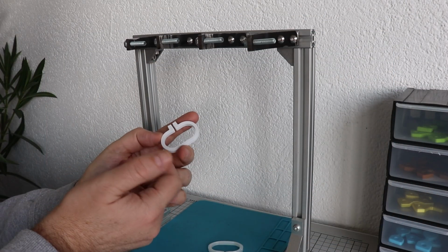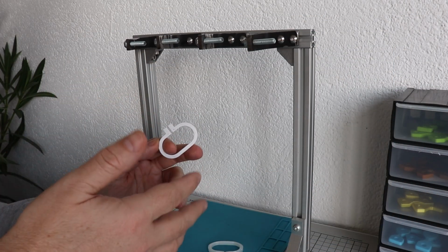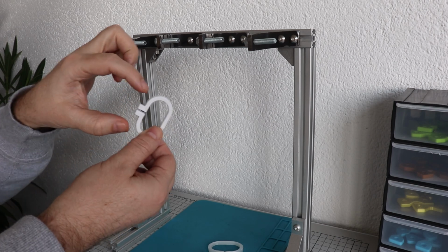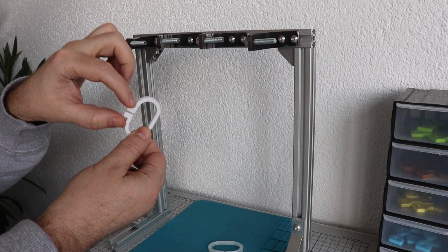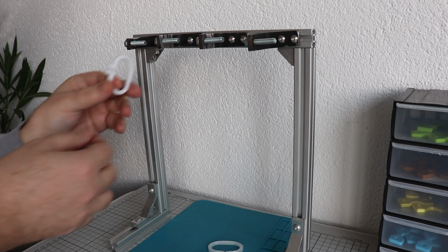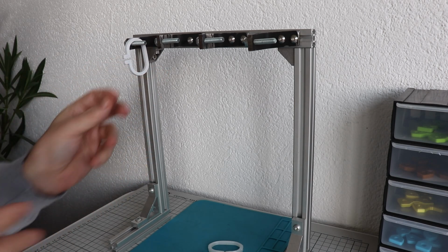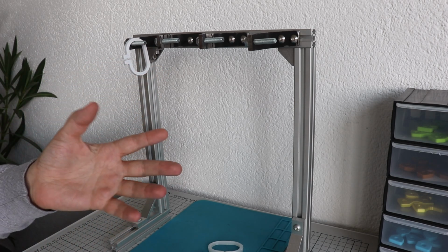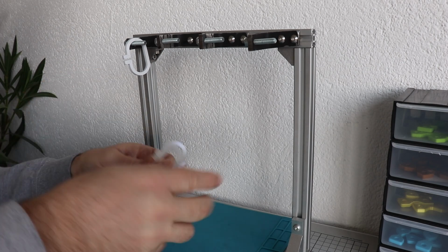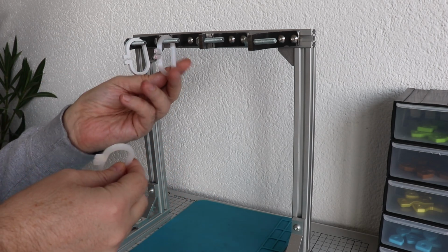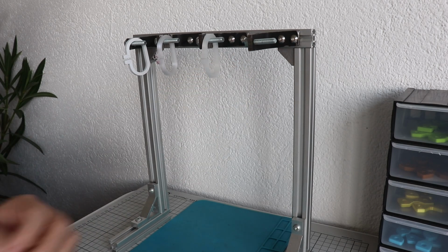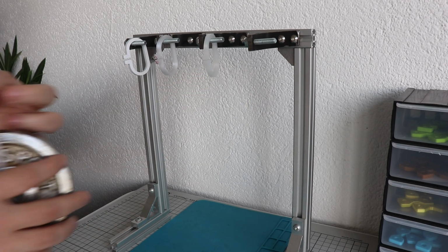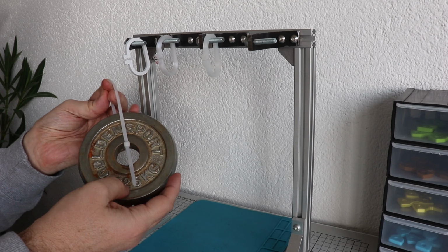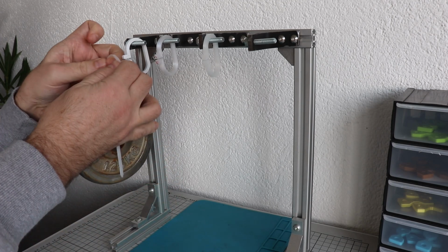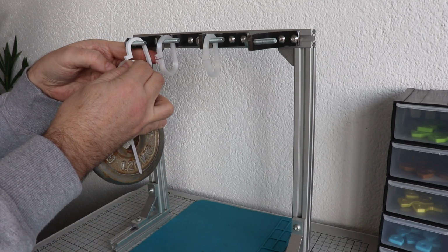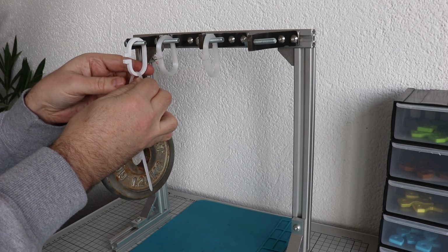I'm starting with preparing a creep test because it will take 7 days. And what is important, the distance between these two surfaces is exactly 12 millimeters. And more about this test you can see in my first creep test video. So this is the ABS, then the polycarbonate and the nylon. And I am adding this 1.25 kilogram load. And I will measure the deformation.